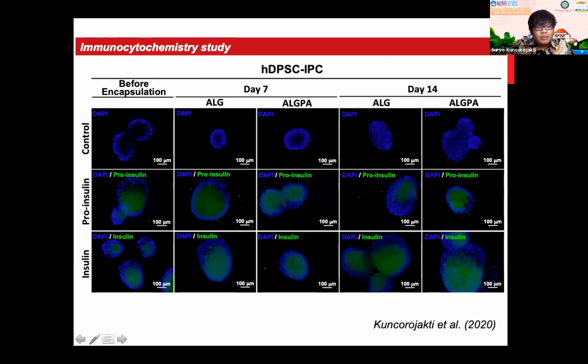A confirmation study was performed using immunocytochemistry as well to detect the expression of intracellular insulin and proinsulin at day 7 and also day 14 post-encapsulation. The result of this study shows that in both encapsulation platforms, alginate and also alginate pluronic, intracellular proinsulin and insulin were expressed at day 7 and day 14 post-encapsulation. A similar expression of intracellular proinsulin and insulin was also observed in mesenchymal stem cell derived IPC in the initial condition, meaning before encapsulation.